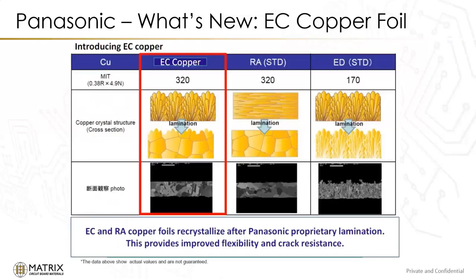So something else to introduce, I was torn between putting this at the end under the new technology, but I think it fits more because it is part of the LCP specifically, and that has to do with EC copper. It's electrically deposited copper, but it takes on a little bit different form. If you look at the structures, we're going to talk a little bit more about copper foil later, but basically the EC copper is electrically deposited, which would be the same as standard electrically deposited, at least from the start with that. But after it goes through the lamination process, the structure changes. So that structure changes to what looks more like a rolled anneal type structure would be.